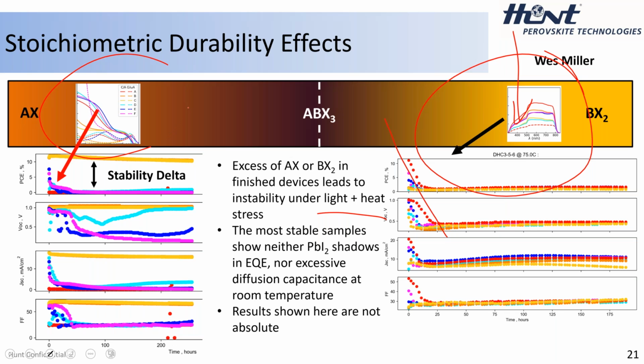Counter to that, we have the same but opposite effect. We have a high capacitance there at the low frequency response in the admittance spectroscopy. And these cells also decompose very quickly, about the same kind of time frame. But we also have two cells on the same substrate that have a proper stoichiometric low frequency capacitance, and those persist. So even on the same substrate, by doing certain things in the process, we can control stoichiometry across the substrate to make it super stoichiometric in one location and stoichiometric in another location, make devices out of that, and see the response.